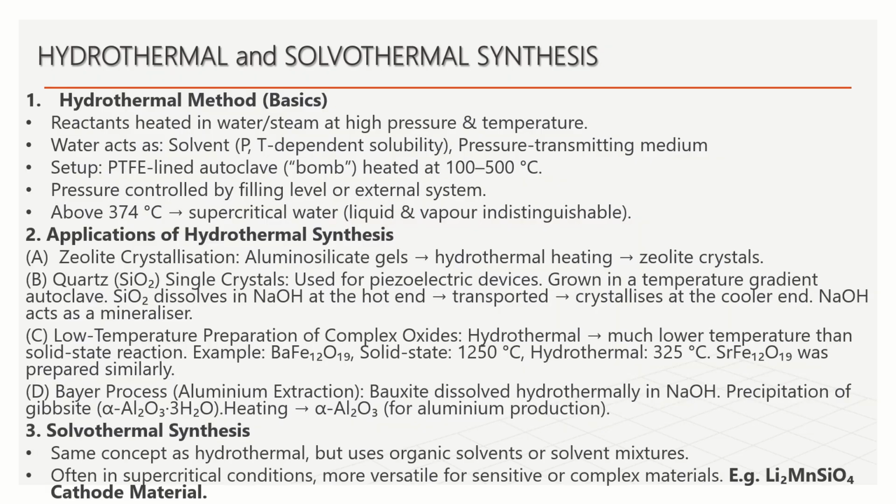Now, solvothermal synthesis is very similar to hydrothermal synthesis, except it uses an organic solvent or supercritical solvent mixtures instead of water. For example, Li2MnSiO4, a battery cathode material, was synthesized phase pure at 300 degrees Celsius and 38 megapascal in just 5 minutes, using supercritical water ethanol.